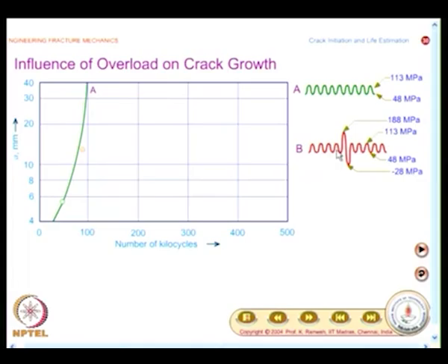Suppose after some time I have an overload which goes from positive to negative, it goes to 188 MPa to minus 28 MPa for the purpose of this graph. And how does the crack growth look like? So, definitely the rate at which the crack grows after an overload going from positive to negative is definitely smaller than what you see when you have constant amplitude, but it has not really benefited the structure.